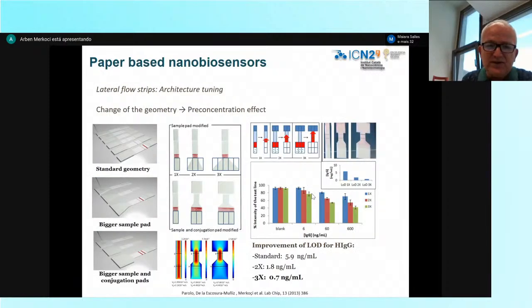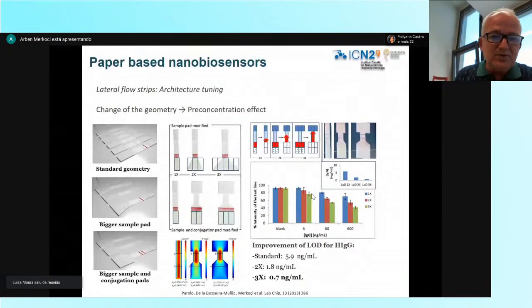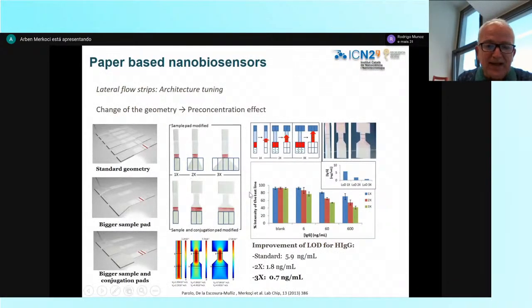Instead of using these gold nanoparticles modified with HRP enzyme, we also did some modification of the architecture. As I explained before, simply by cutting the paper, we are able to change, for example, the sample pad or the conjugation pad. And you can imagine that when these changes happen in the geometry, the microfluidics is going to change. In fact, we did some simple calculations. We modeled these microfluidics and found out how this was changing depending on the geometry. In this way, we are able to tune the performance of the lateral flow based on the geometry of the system, which is in fact very simply done. So this is another way that we could, for example, extend or shorten the operation range, increase or decrease the sensitivity and detection limit according to the application.